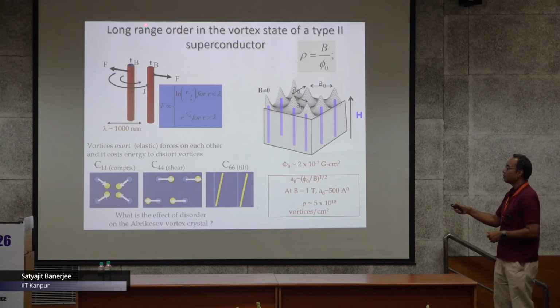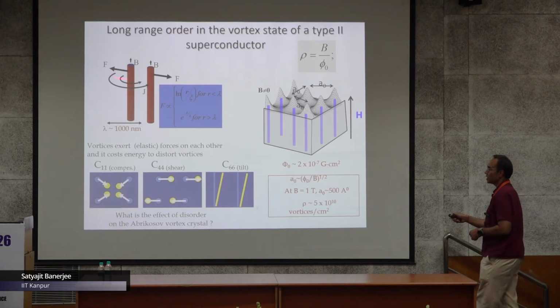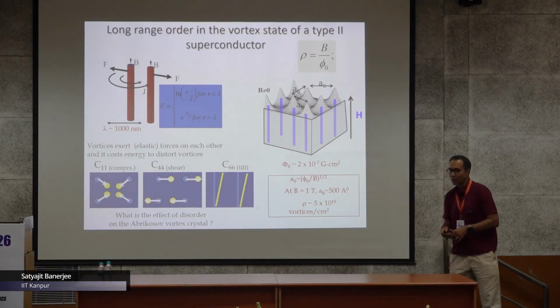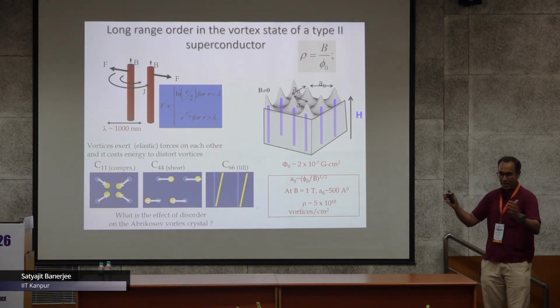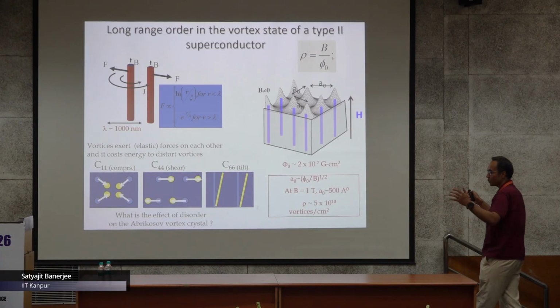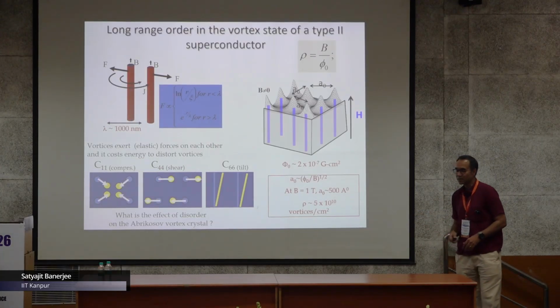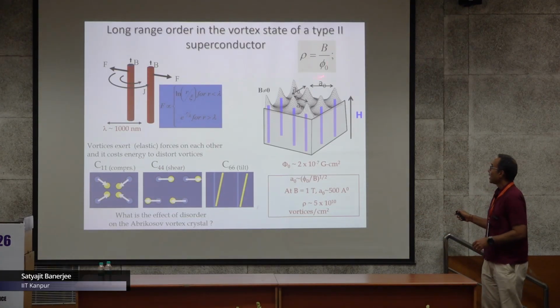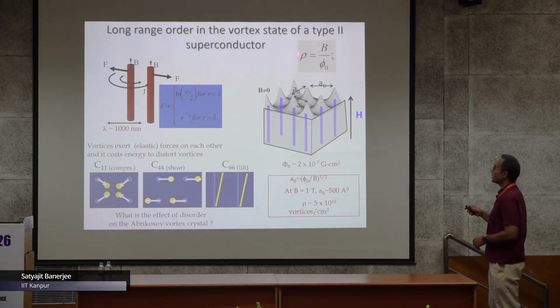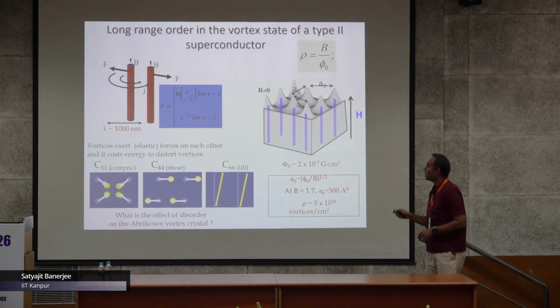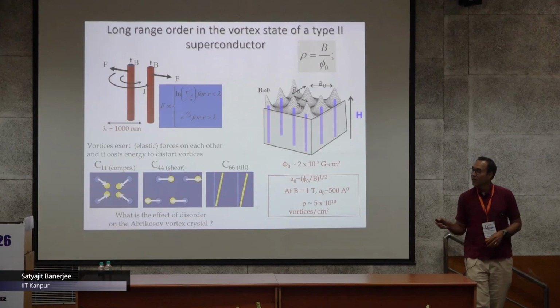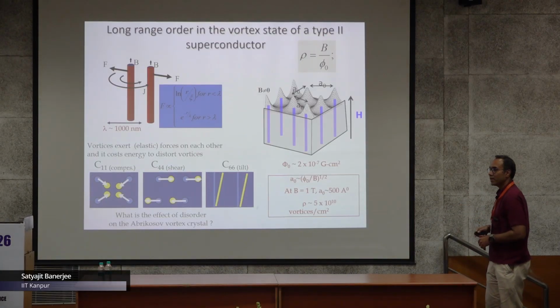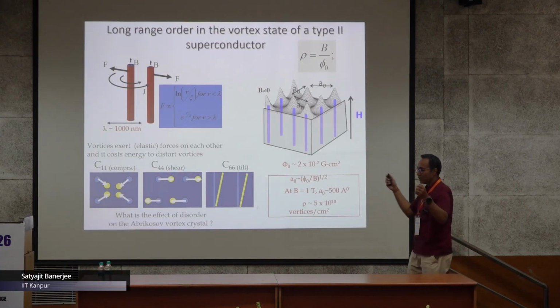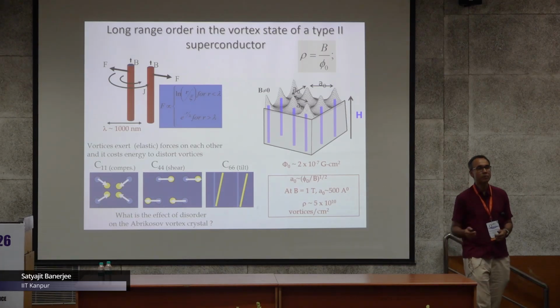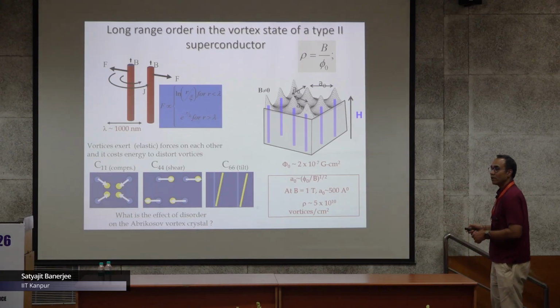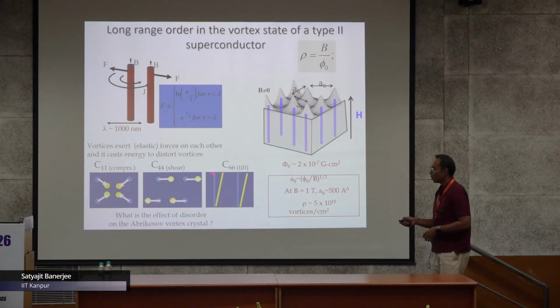These are interacting particles because the current around a vortex interacts with the magnetic field of another vortex, and there is a repulsive interaction. The external field tries to order and pack them together, so there's an interaction between vortices. What's nice is that this interaction can be controlled by the magnetic field, since the density of vortices is directly proportional to the field. So if you change the magnetic field, you can bring vortices close together or move them far apart, and play with the interactions between them.